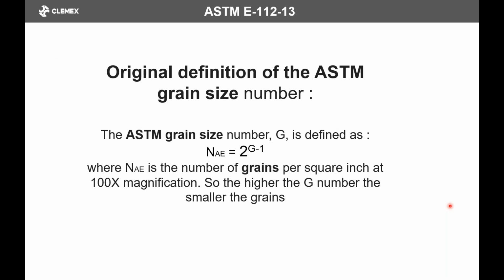Now, the original definition of ASTM grain number is the number of grains per square inch at 100x. So that's the formula that we have here, and this is now used with a more elaborate formula. What's important to remember as a rule of thumb is that the higher the G number, the grain size number, the smaller the grains. That means that there are more grains that fit within the square inch. So that's the idea of the grain number getting higher, similar to buckshot, I guess. It's the same principle. When you have more pellets in a certain area, the value increases. So that's more grains.